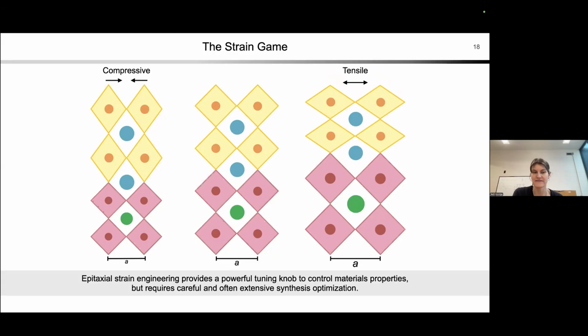And so on the left, you have what we would call compressive strain. As you put something onto a material with a smaller lattice constant, it gets kind of squished in, but then it expands outwards to kind of make up for it. Versus on the right, what you see is tensile strain. We put that material down and it stretches out, but then you see it kind of compresses in the other direction. So we're going to come back to strain a few more times.